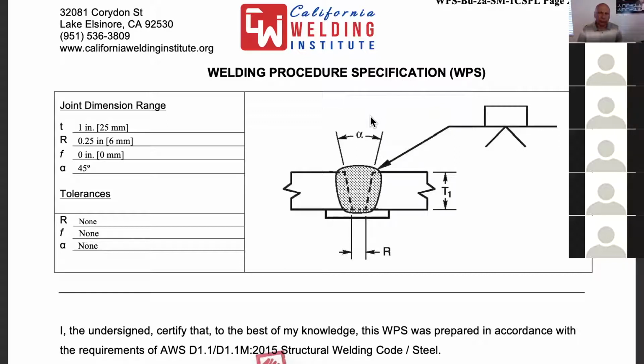If I'm testing a welder on pipe, and the inspector wants to inspect the root, is he looking inside the pipe or outside the pipe? Obviously, he's looking inside the pipe. So we need to go to the root side and inspect. The problem is, we have a backing in the way. Well, that's not a problem. We remove it. Then we inspect the fusion to the corners of both members being welded, and there cannot be any lack of fusion, any cracks, or any inadequate joint penetration.